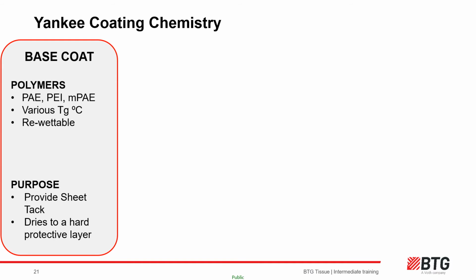Base coats are polymers, for example derivatives of polyamide-epichlorohydrin resins, or polyethyleneimine. Each product type will dehydrate but become tacky at different temperatures. The temperature at which the polymer transitions from a fluid liquid to a solid and is at its tackiest is called the glass transition temperature, capital T, small g. The base coat will reach glass transition before the nip on the tissue machine and then must re-wet. That is, it becomes tacky once more with the contact from the wet sheet to accept the sheet onto the coating layer.